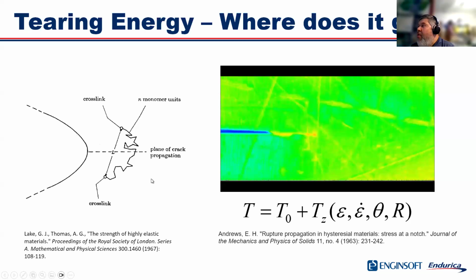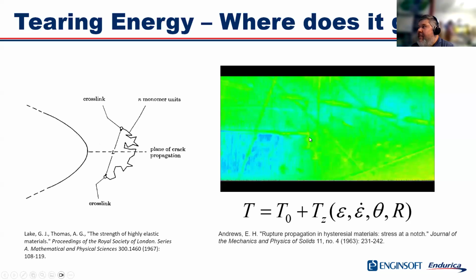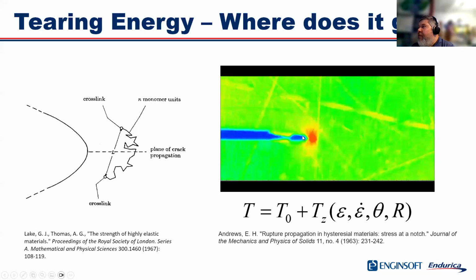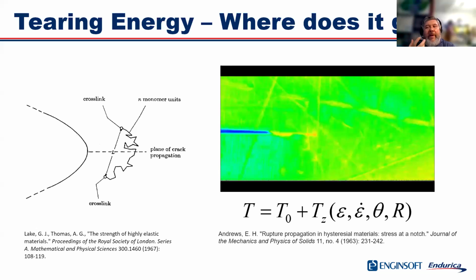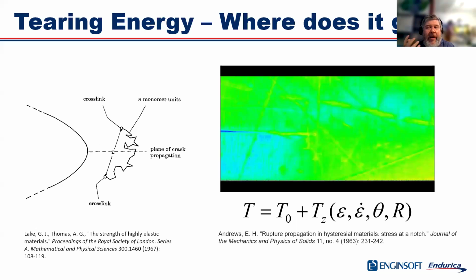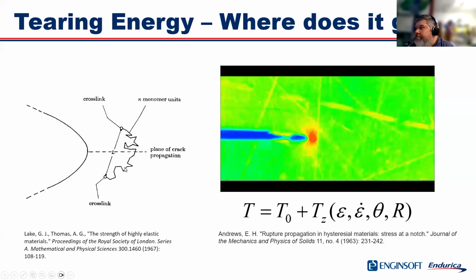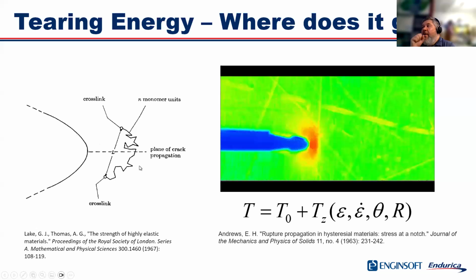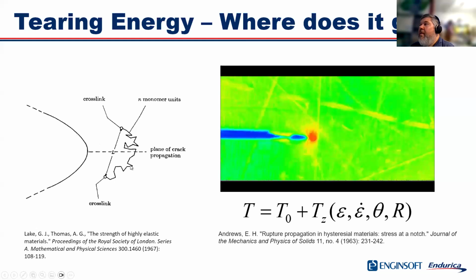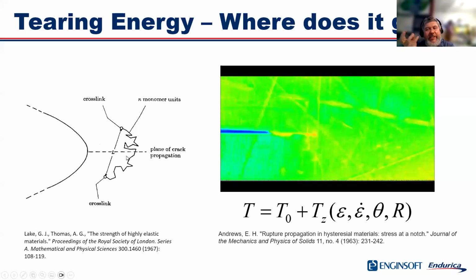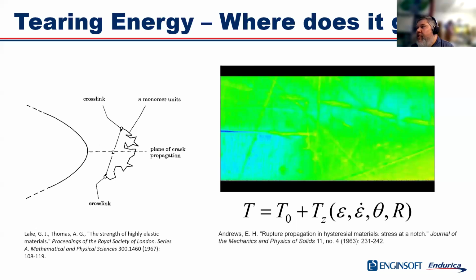And what we know is that if you want to grow a crack, then every polymer chain, right? Rubber is a polymer, long chain molecules. But in order for a crack to grow, every single polymer chain that crosses the plane of the crack must break. And in order to break each individual chain, there is a required amount of energy. It's the bond breaking energy for these carbon-carbon bonds in the main polymer chain. So it's the energy to break a chain, and then it's also how many chains per unit cross section area, right? And the product of those two things gives you the tearing energy.